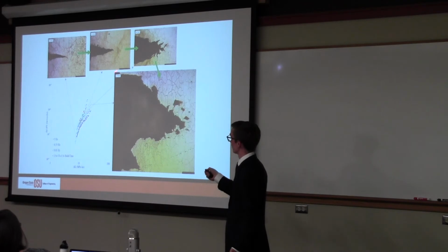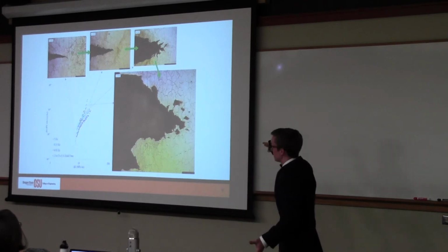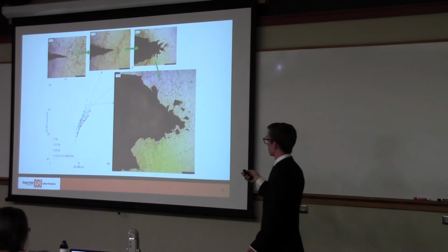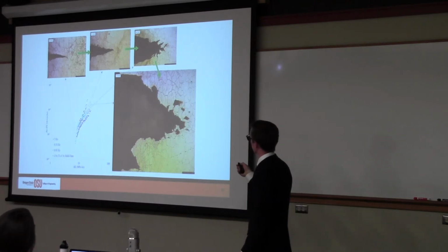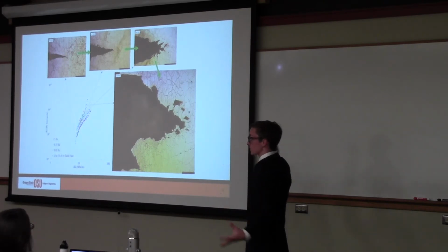Or right at the threshold, and we see this amazing little profile. Right at the threshold, everything branches. And this is how the transition in behavior happens, the transition towards time dependence. Voids are forming. If you polish this thing down, you see a void there, you see a void here, you see a void here. Voids are forming, and the crack branches into all the voids.